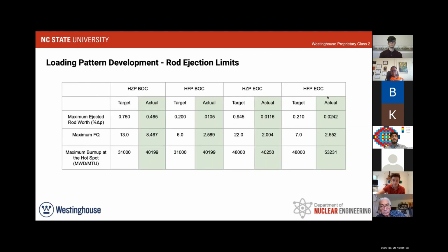Thank you. The rod ejection limits. This is a safety analysis that we ran, and for conservative measures, we assumed that the highest rod worth would be the rod that would be ejected from the core. As you can see, we ran the rod ejection safety test at both the beginning of cycle and end of cycle, and in both the hot zero power and hot full power scenarios. We successfully met the maximum ejected rod worth and the maximum FQ for all these scenarios.